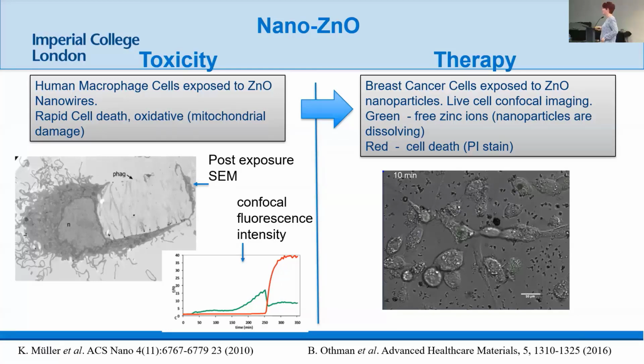And the red signal here is a dye that stains the nucleus of the cell. So you see red if the cell is dead, and you see green as the zinc dissolves. And you only ever see red after you see this increase in the green, right? So the death is correlated to the dissolution. So this is a human macrophage cell, and we see all kinds of damage in situ.